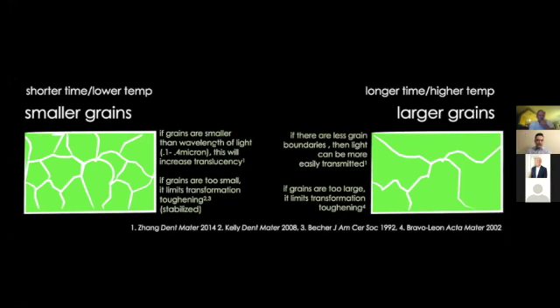And same thing with strength: if the grains are too small, then the zirconia won't transformation toughen, so it can't go from the tetragonal phase and get bigger. Same thing if they're too big, then they can't transform. So there's kind of a happy medium there. So the point of this is it's too complicated to try to guess what's going to happen.